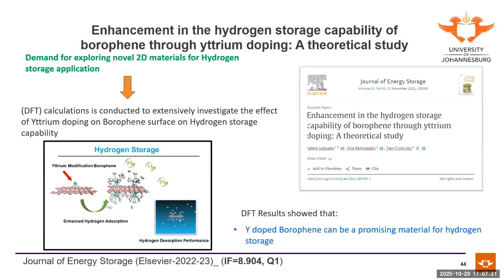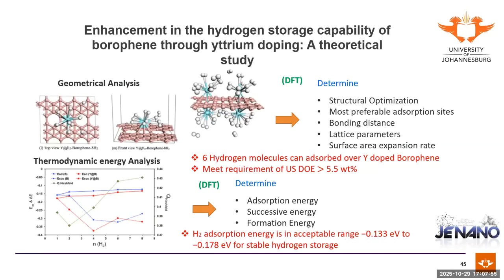All right, there's some work from my publications. This one is from the Journal of Energy Storage: Enhancement in the Hydrogen Storage Capability of Borophene through Yttrium Doping. Of course, this is a theoretical DFT study. The result shows that yttrium-doped borophene can be a promising material for hydrogen storage. Through geometrical analysis, we found that 6 hydrogen molecules can be adsorbed by yttrium-doped borophene. When we calculate, this meets the requirement of the US DOE target for 2025, which is 5.5 weight percent. Actually, I think they have the latest showing that the optimum they want is 6.5% in the future.